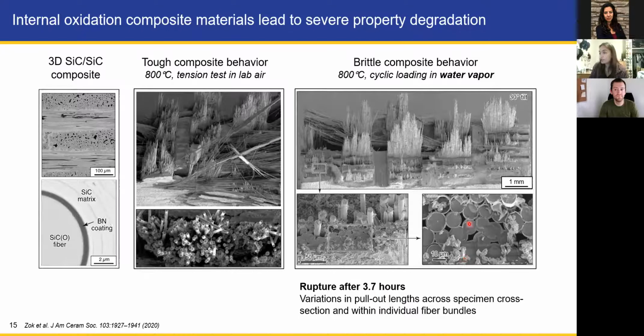And if you take a closer look at the microstructure in the SEM, you see new species start to form, particularly around those really important boron nitride coatings. So we want to figure out what is happening when water vapor is introduced. But this picture, like I mentioned, is a little bit too complex to understand what's going on because we get such different behavior just within the same sample.